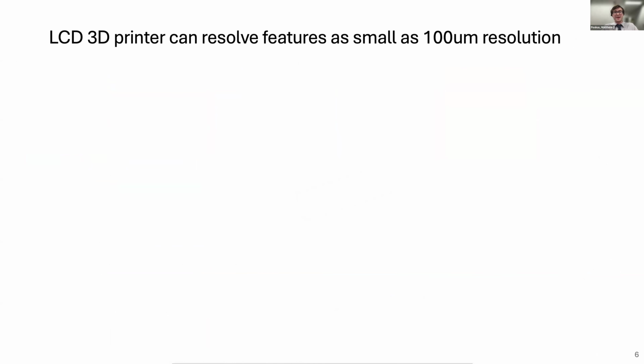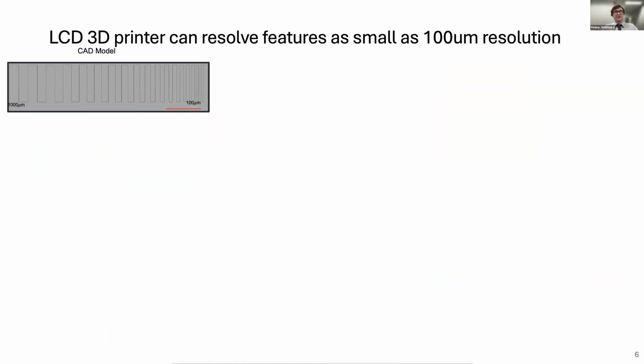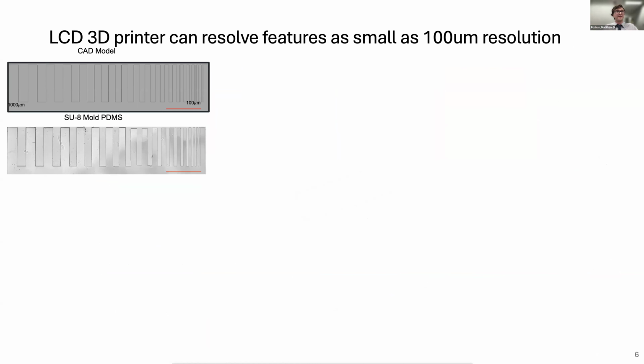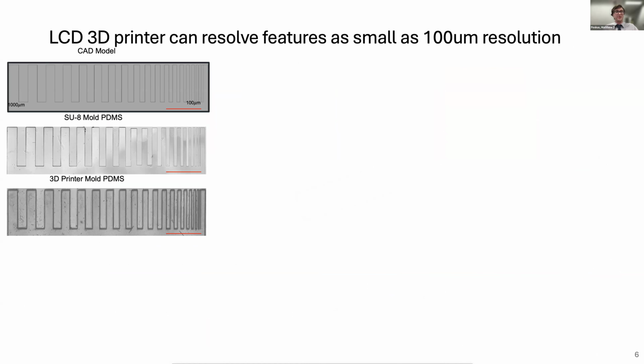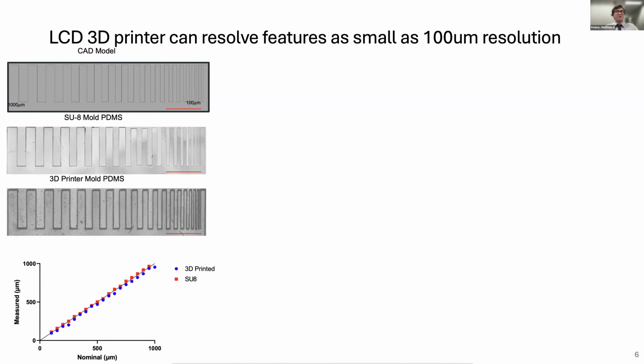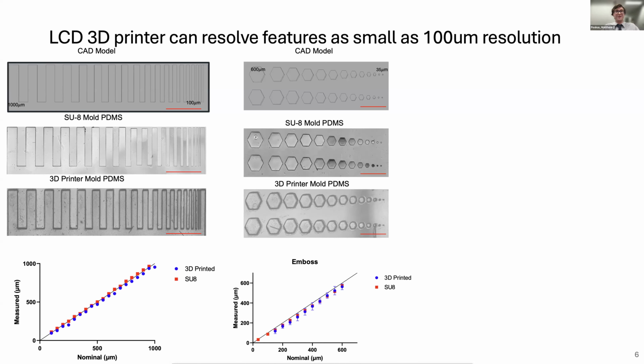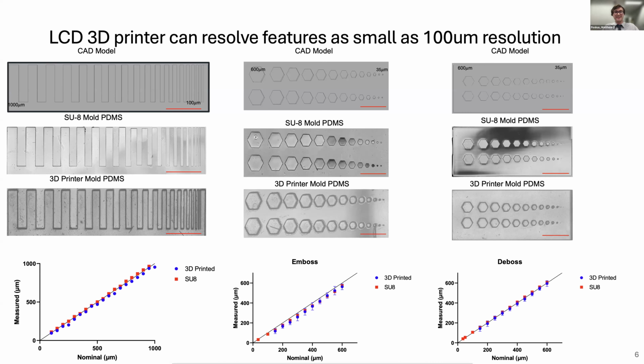The next step was to characterize the resolution limits using these optimized settings. To do that, we printed lines of varying width, ranging from 1,000 to 100 microns, for both an SU8 mold and a 3D printed mold, and we compared the PDMS. We found that we can resolve features with the 3D printer down to about 100 microns. We also repeated that for both embossed and debossed geometries, so positive and negative features. In this case, we used hexagons, and we found that we can again resolve these hexagons down to about 100 to 120 microns.